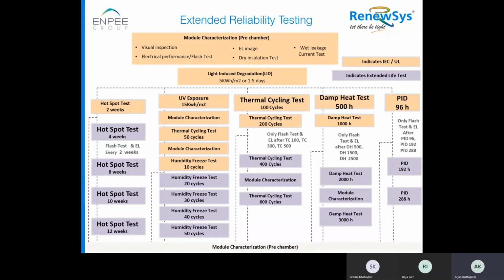What we discussed is that we do extended reliability. Basically, the tests highlighted in orange are as per IEC or UL, that is IEC 61215 and IEC 61730. But we go beyond IEC, basically 3 times IEC. That is indicated in purple color here, extended IEC test. The same way we follow for our reliability monitoring program: once every 60 days, we take random samples and do all these tests as per IEC, and we extend the test for 3 times.